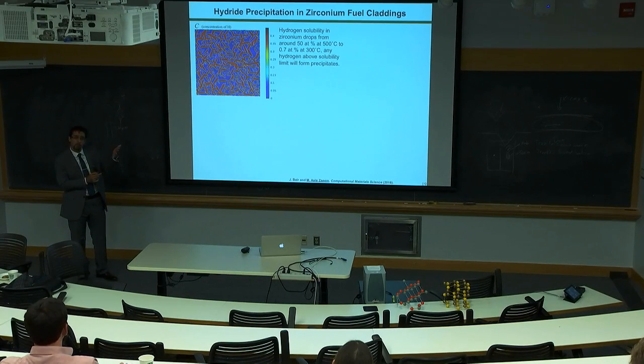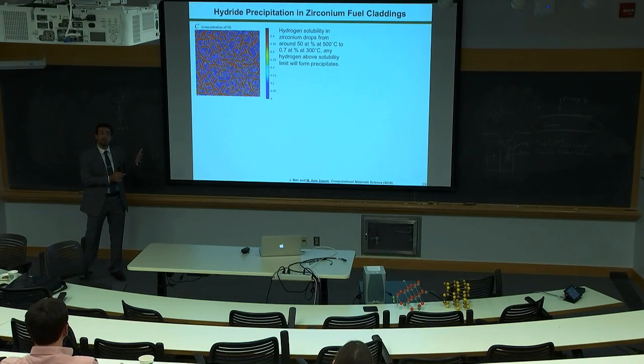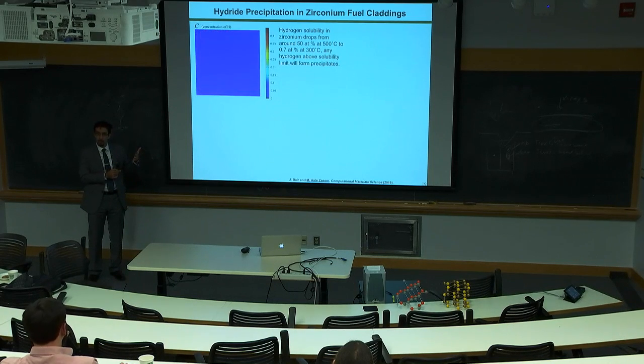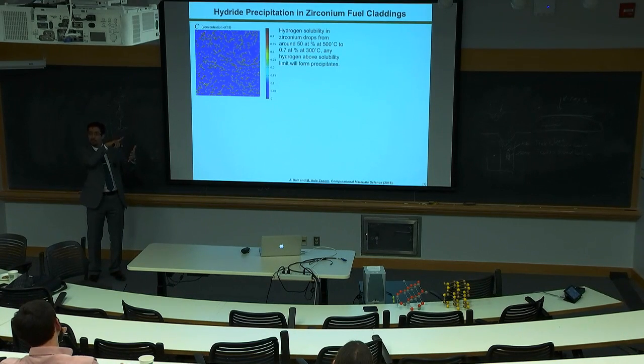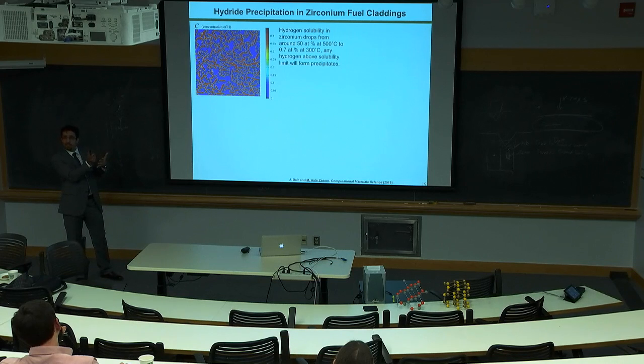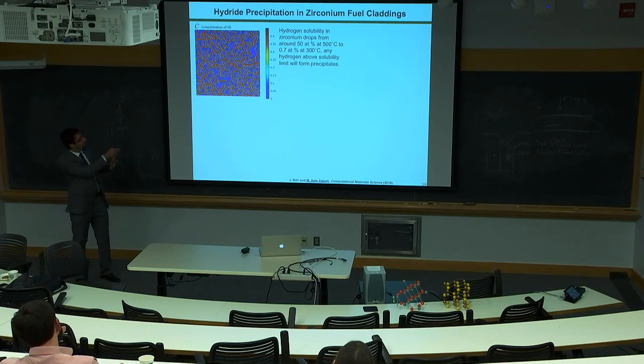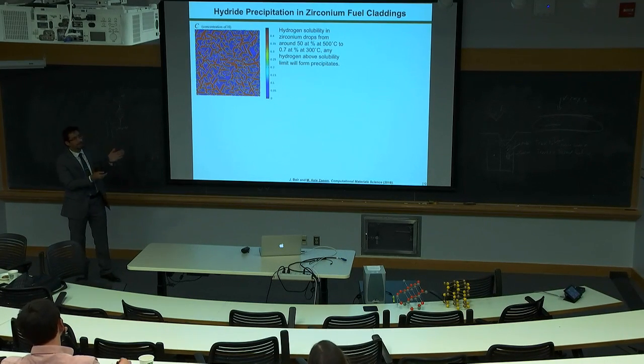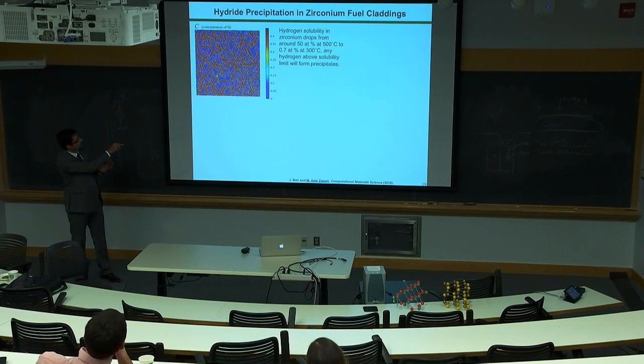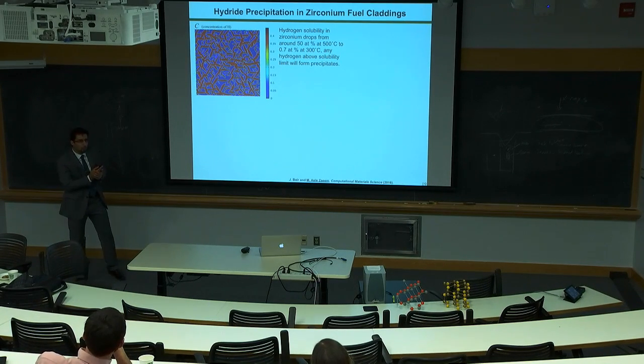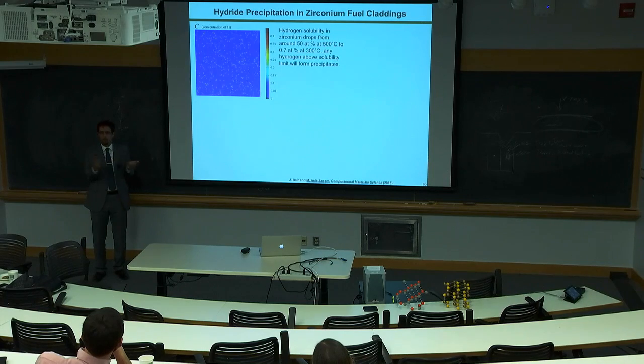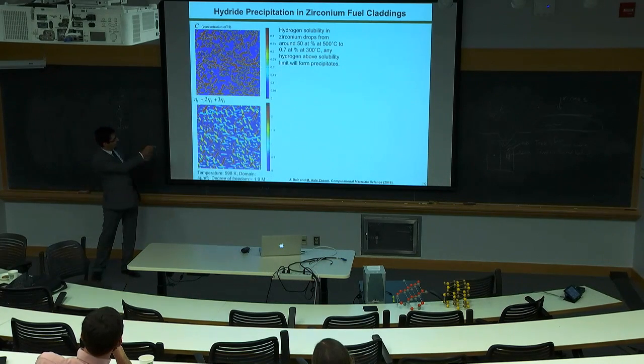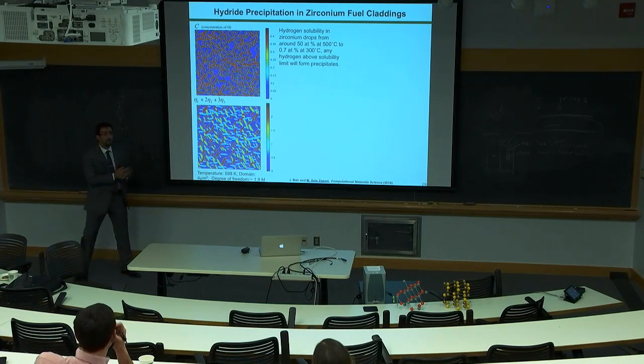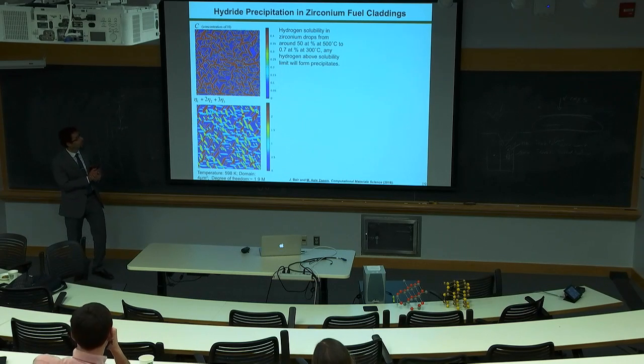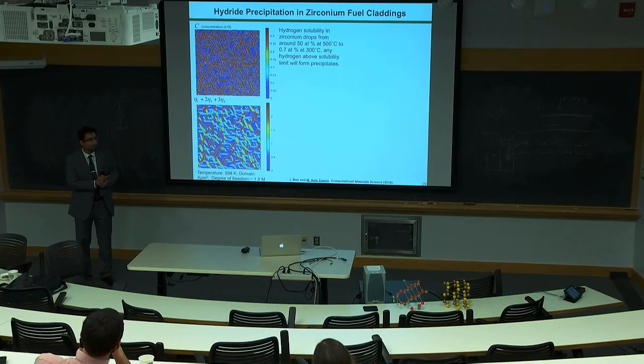These are preferred orientations. Zirconium is a hexagonal close-packed material, so it has six-fold symmetry, like 60-degree symmetry. Okay, and they tend to accumulate at the basal plane, so these are at 60 degrees. So we needed three order parameters just for orientation. So this is the map of orientation of those precipitates. Okay, what else can this model predict?